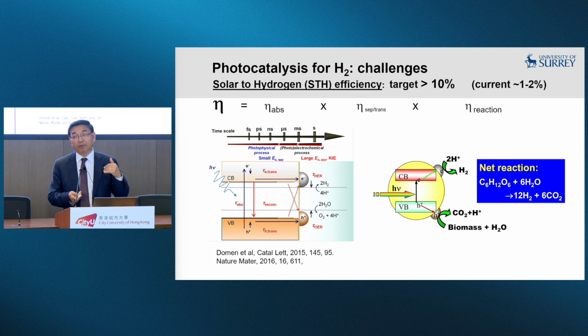Of course, by electronic structuring, doping, heterostructuring, you can change the band gap, you can change the electronic structure, then you can optimize at the femtosecond level. But also at the reactor level, of course, you have to improve the surface area, the flow, and all that reactor design comes into play. So the key is to reach a solar-to-hydrogen efficiency of about 10%. At the moment, it's very hard to get there.